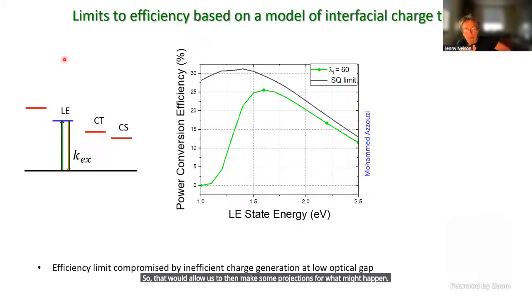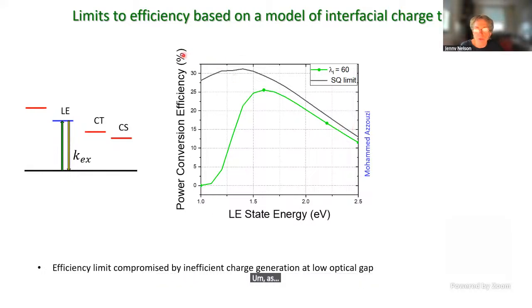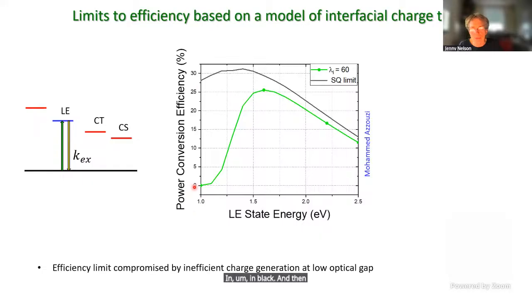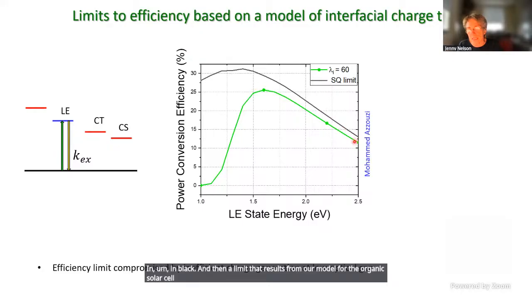So we take that model, and now we can work out a kind of limiting efficiency for our organic solar cell, as compared to the limiting efficiency for the ideal conceptual solar cell that was studied by Shockley and Queisser. The Shockley-Queisser limit is shown here in black, and then a limit that results from our model for the organic solar cell is shown in green.